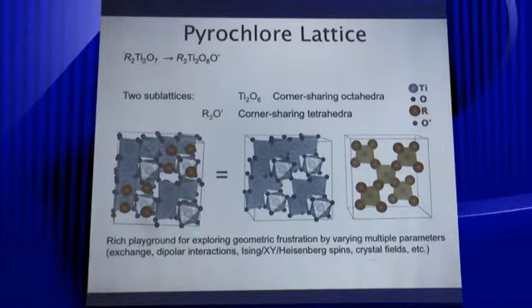But the pyrochlore lattice, even though I'm only emphasizing the pyrochlores today, traditionally they were studied because there's a prediction that for nearest neighbor antiferromagnetic interactions on the pyrochlore lattice for Heisenberg spins, you should have no long-range order. But it's actually a rich playground for varying these parameters, right? So looking at what happens when you have anisotropy, when you have exchange interactions, dipolar interactions, crystal fields. And all those would be important when you're trying to determine if you have a spin ice or not.